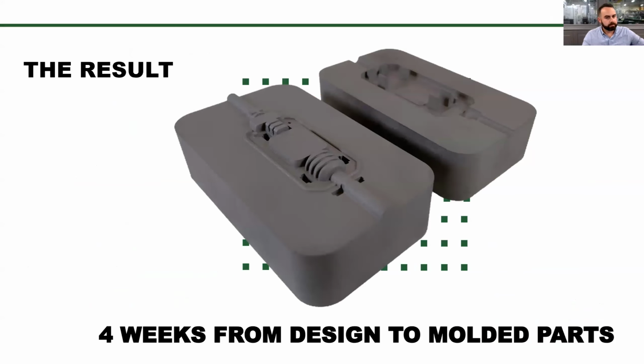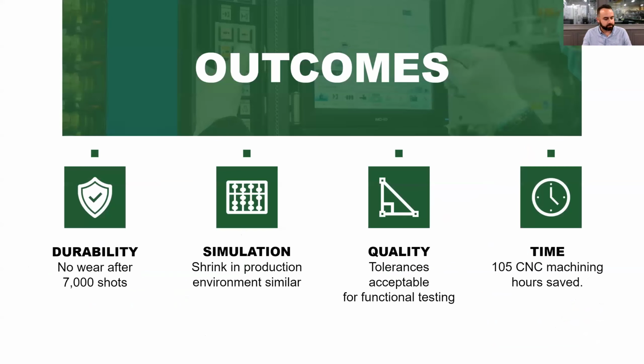So obviously the end goal was to get parts into our customer's hands within 4 weeks, and we achieved that goal. We were able to mold about 1,000 parts, or 100 parts, within 4 weeks. All of the criticals that came off of the cavities were plus or minus 3 thou, and we only had flash in one area.